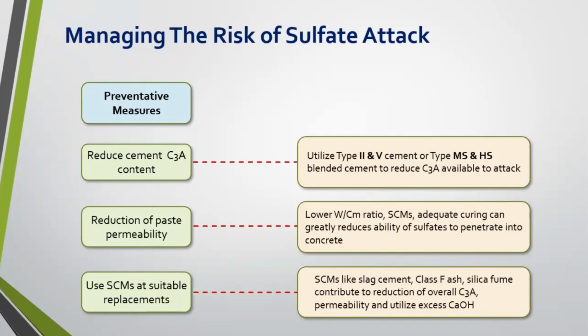Adequate curing. This is one that gets overlooked a lot, but adequate curing can greatly reduce the ability of sulfates to penetrate into concrete. And then use of SCMs at suitable replacements. Slag cement, obviously, Class F fly ash, silica fume, all of those contribute to reduction of overall C3A and permeability, with the added benefit that all of those particular SCMs will utilize excess free lime in your concrete mix and produce additional CSH, or calcium silicate hydrate. Again, that's the good stuff that we want more of, reducing permeability and giving us incredibly durable concrete.